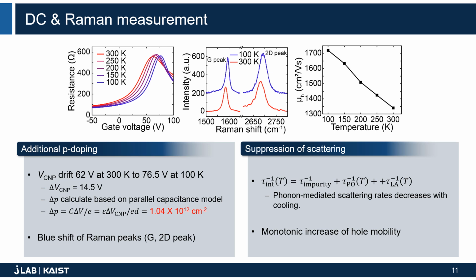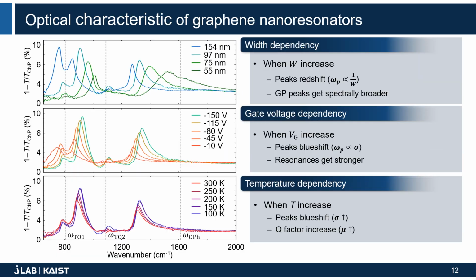This feature can be described using three different scattering mechanisms: impurities, silicon dioxide polar optical phonons, and the longitudinal acoustic phonon in graphene. According to past research, impurity scattering shows little temperature dependence. On the other hand, phonon-mediated scattering rates rapidly decrease with cooling. The mobility measured in our experiment shows a near-linear dependence on temperature, which agrees well with the previously reported measurement at high doping concentration. Then let's move on to the optical characteristic of graphene nanoresonators.